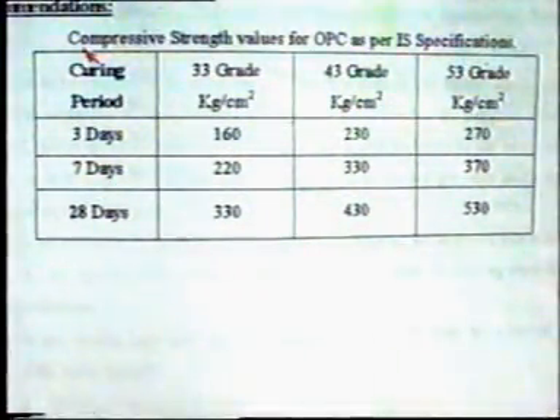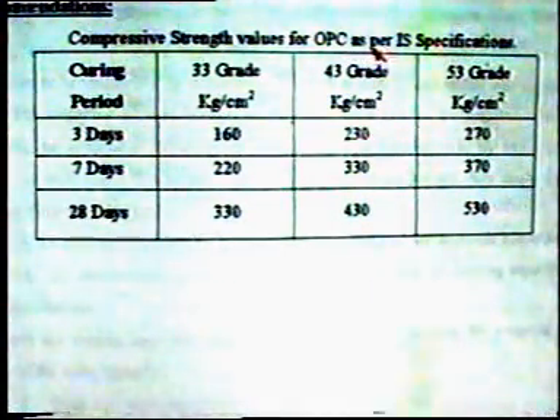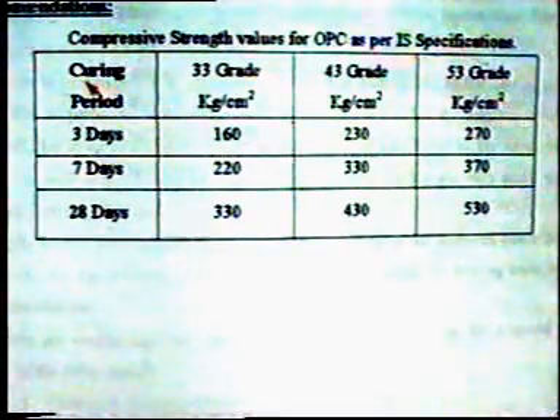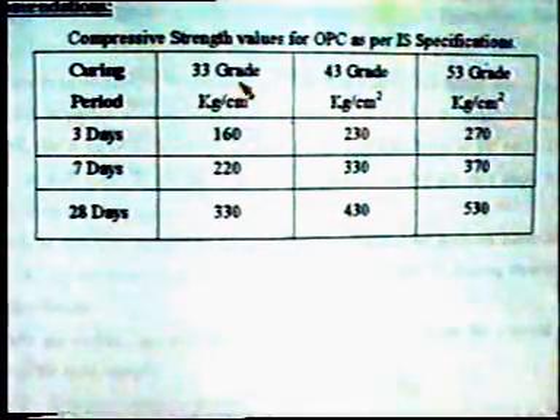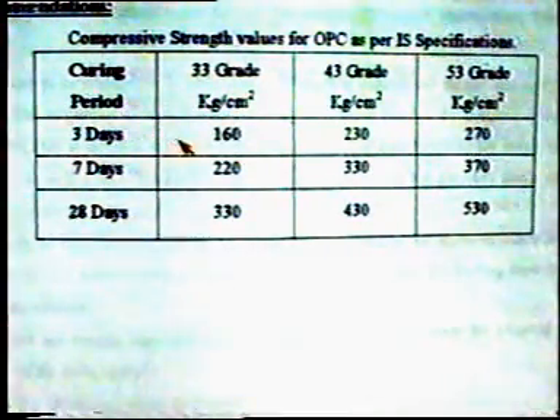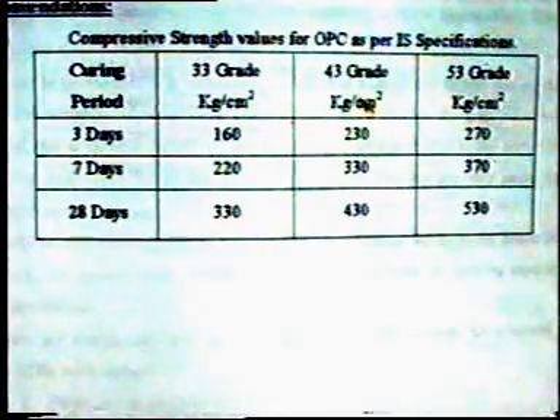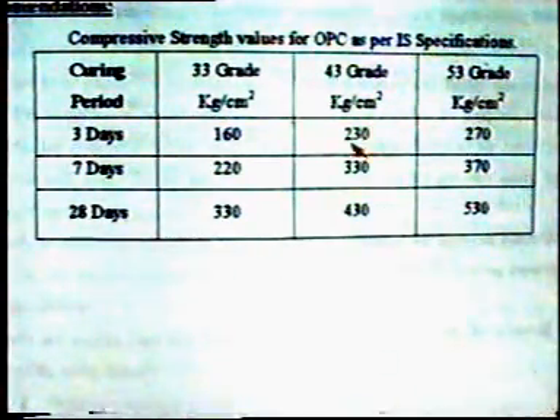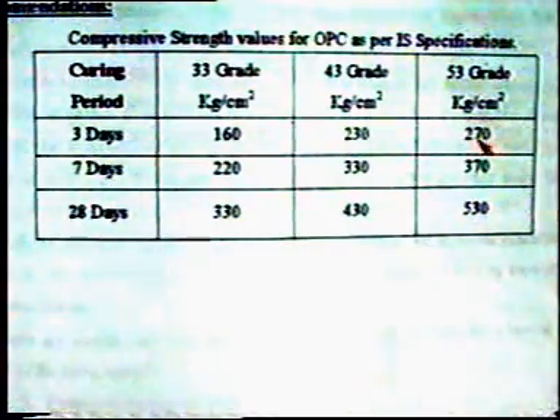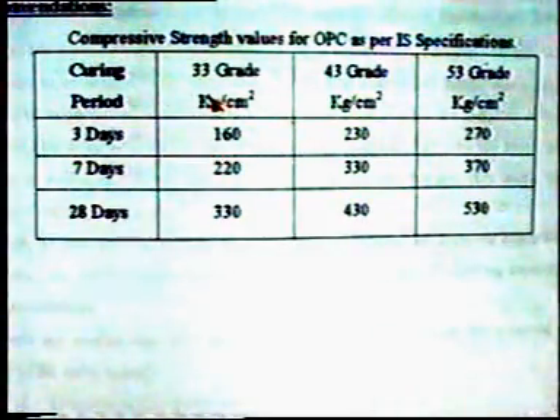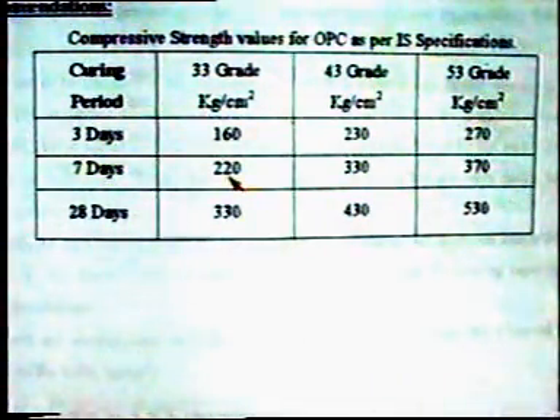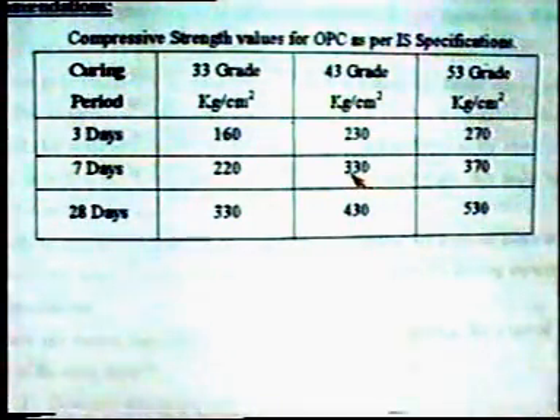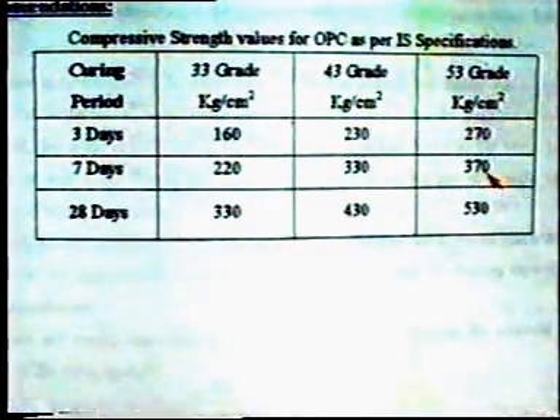Recommendations of the compressive strength values of the ordinary Portland cement are as follows. For 33 grade cement, on 3 days testing, the compressive strength should not be less than 160 kg per centimeter square. For 43 grade cement, it should not be less than 230 kg per centimeter square. For 53 grade cement, it should not be less than 270 kg per centimeter square. On 7 days curing, for 33 grade cement, it should not be less than 220 kg per centimeter square. For 43 grade cement, it should not be less than 330 kg per centimeter square. For 53 grade cement, it should not be less than 370 kg per centimeter square.